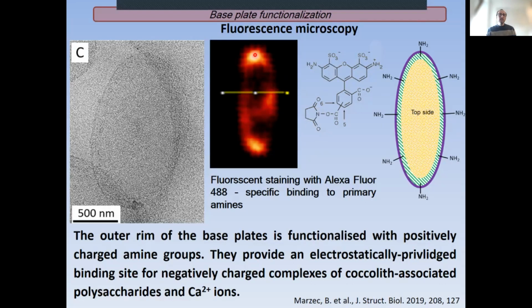And we can see that the staining is not perfect, but it's mostly localized around the rim of the base plate. What this is suggesting is that the rim of the base plate is functionalized with primary amines that are going to be positively charged, and they're going to be providing an electrostatically privileged binding site that can attract or bind to negatively charged complexes of polysaccharides and calcium ions.